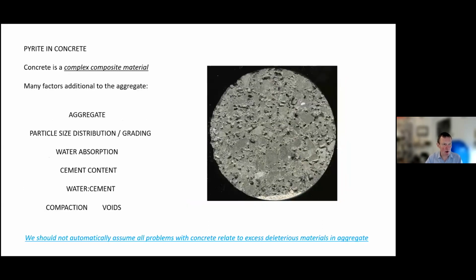I have to stress that concrete is a complex composite material, and there are many additional factors in addition to the aggregate and in addition to deleterious materials that we must take into account. There's the particle size distribution or grading of the rock. There's the water absorption of the rock and the concrete. There's the cement content. There's the water cement ratio and manufacture, and there's the compaction and voids. And all of these interplay with each other to make a durable or not durable concrete. We should not automatically assume that all problems with concrete relate to excess deleterious materials in aggregate.